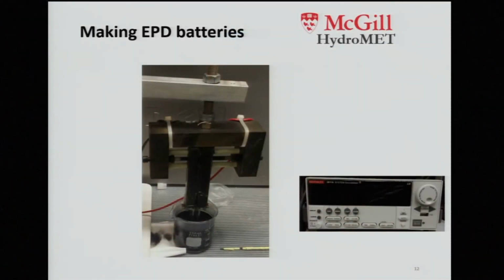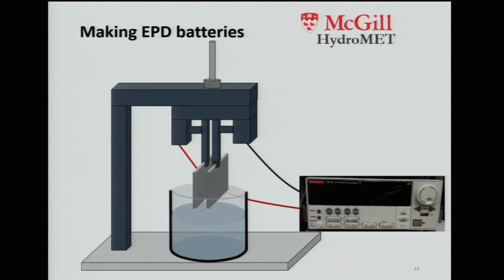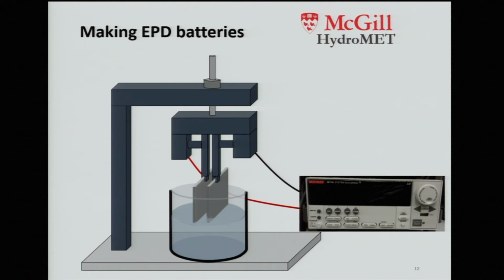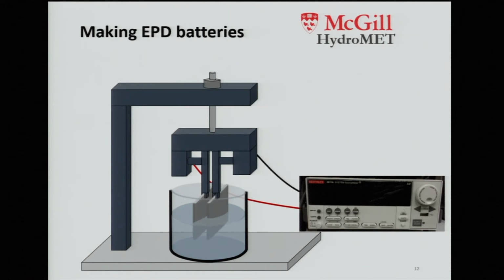Now, within the McGill Hydromet group, we use this submersion setup hooked up to a power source to make our electrodes. This is a bit dirty, so let's look at a schematic I drew. And the submersion setup consists of an adjustable height bar that holds the two metal surfaces in place and connects it to a power source. So the way we make our coatings is we submerge the metal surfaces. And once it is submerged, we apply a voltage. And this is very brief. It's only done from anywhere between 5 to 15 seconds. This forces a coating to form.